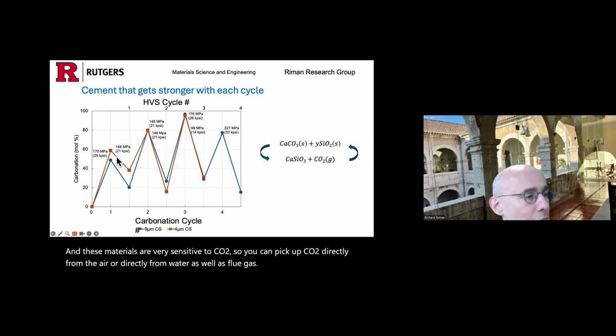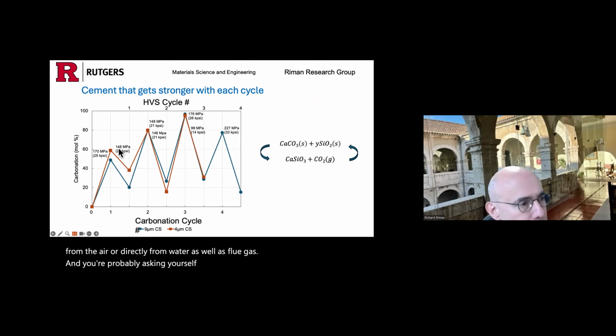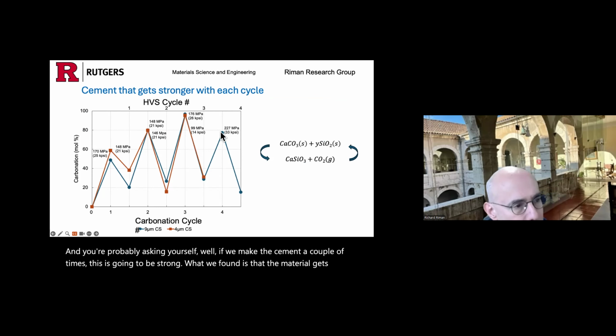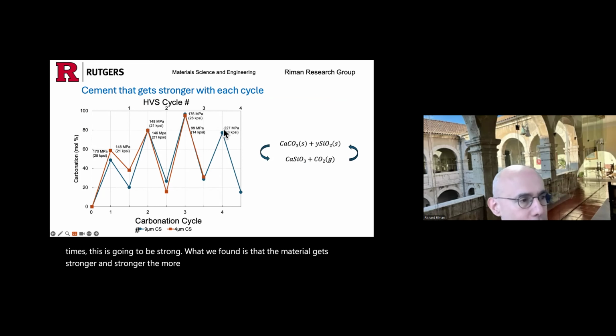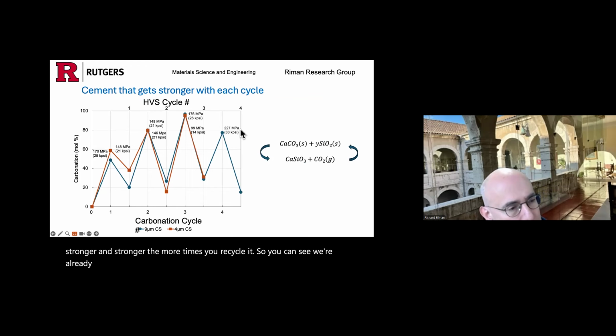And you're probably asking yourself, well, if we make the cement a couple of times, is it going to be strong? What we found is that the material gets stronger and stronger the more times you recycle it. So you can see we're already over 200 megapascals, and that's more than 3 times the strength of Portland cement.